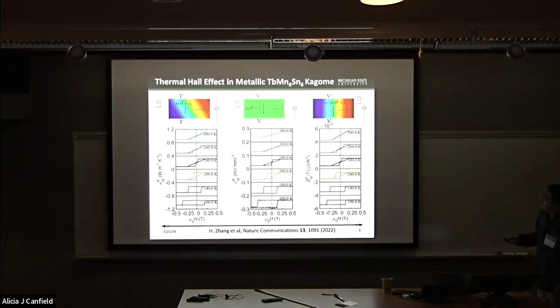Again, the thermal Hall effect has been applied to study metallic compounds. Recently we have applied such a technique to study the terbium manganese tin one sixty-six compound, which is a Kagome magnet. We measured various transverse transport, including the thermal Hall effect, Nernst effect, and the electric Hall effect. For this particular compound, we observed very large transverse signals for all three transverse transports. This tells us that the system is topological in nature.